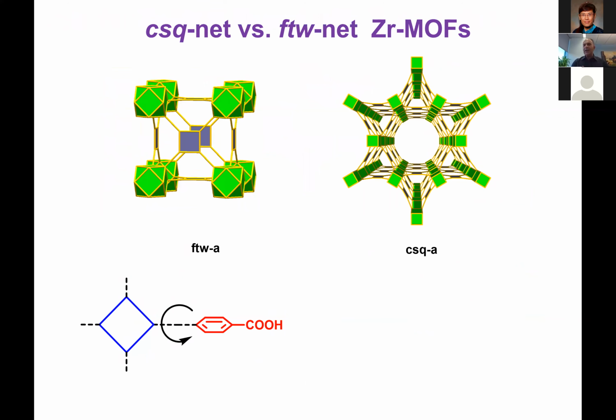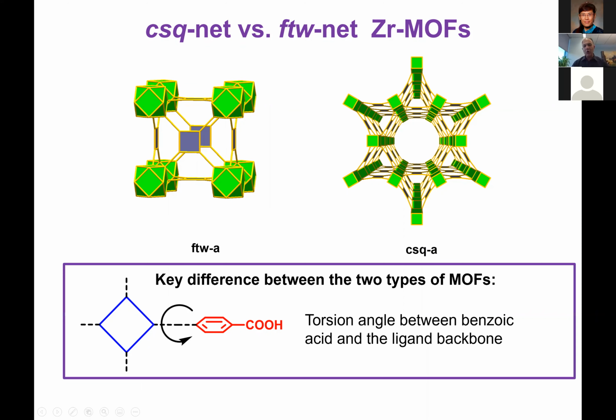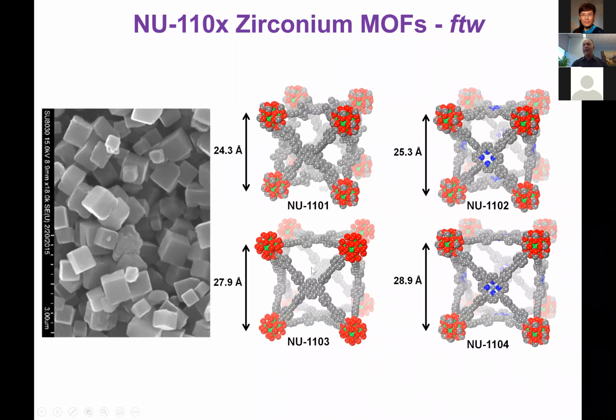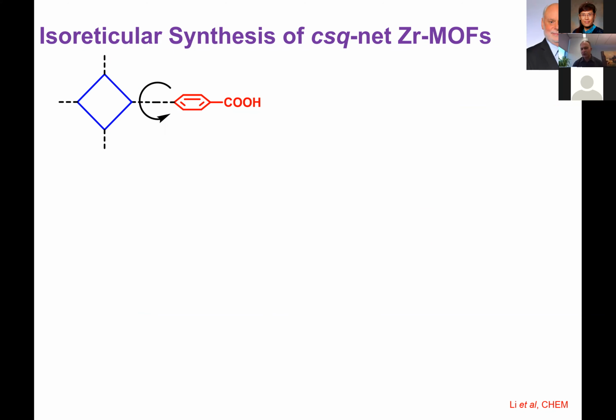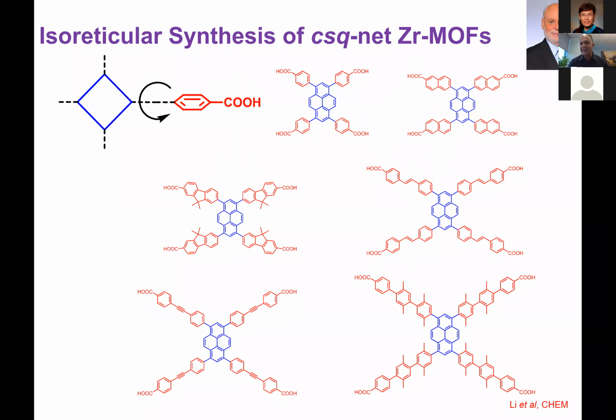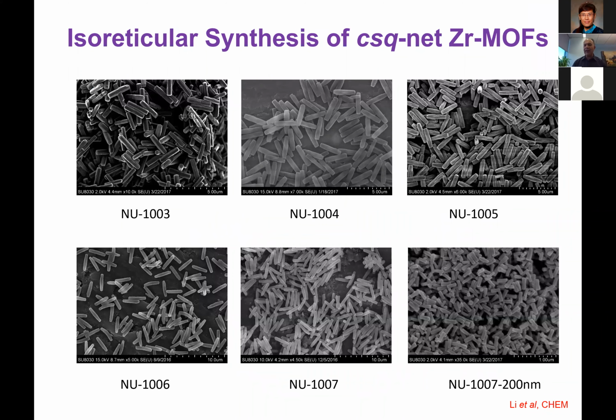We learned that the torsion angle around the phenyl that has the carboxylic acid and the center of your linker matters. What does that mean? If you have a linker whose torsion angle is 0, you will get the FTW. If you have a linker whose torsion angle is between 55 and 65 degrees, in collaboration with Fraser Stoddart, my colleague, we were able to make all these ligands with the right torsion angle, and you could tell without actually getting a crystal structure, this is not the box-like topology.